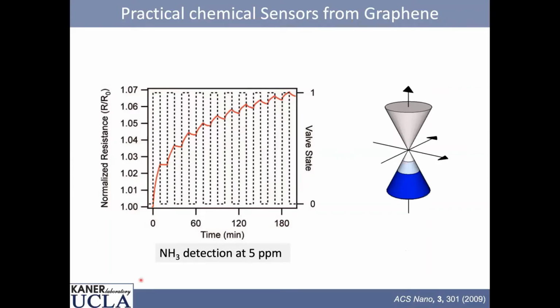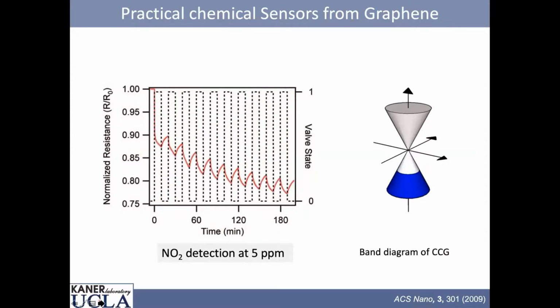Now, if that's true, I should be able to withdraw electrons and see the inverse effect. So here we go. NO2 withdraws electrons at 5 parts per million. And every time we bring in NO2, we're lowering the resistance. In other words, we're increasing the conductivity. So what we think we're doing is we're p-doping a little bit more, making it more conductive.